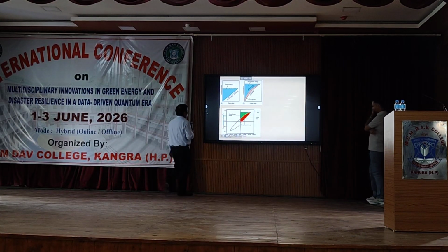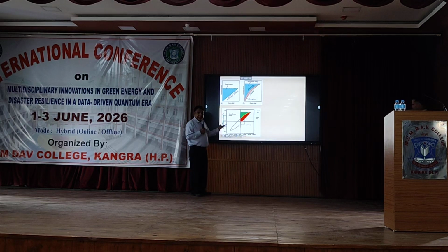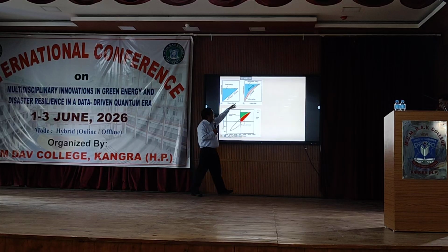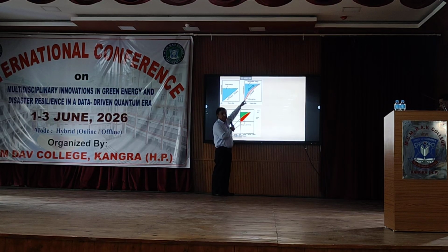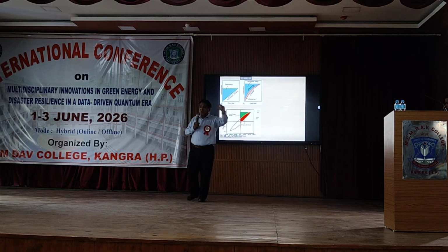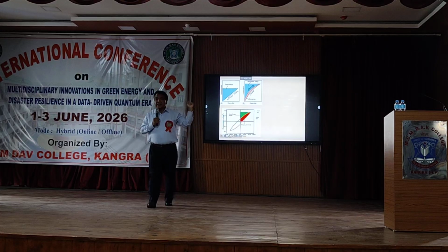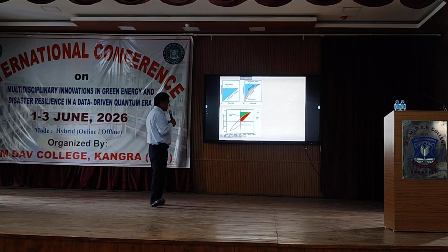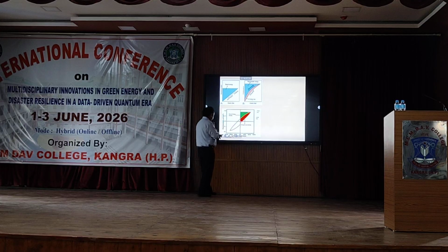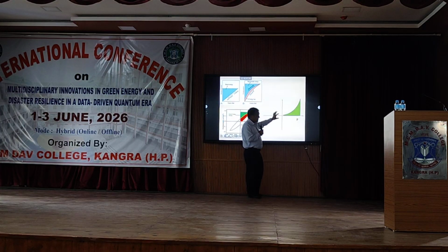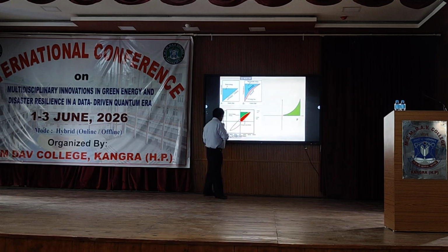So one can calculate the recoverable energy and the loss energy, and total energy, just by the area under this curve, and the area under the second curve. Subtraction of the second area from the first area gives you the area under that light pink color, which is the loss energy density, and so one can calculate all of these parameters. That is an elaborated way to understand how we calculate the area under this curve.